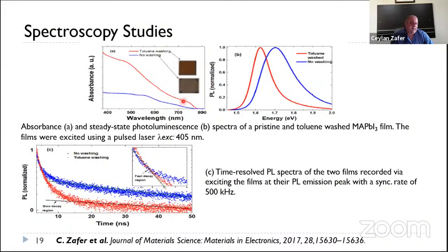This is also checked with the absorption and electronic spectra, and this makes a small difference in the optical properties of the perovskite. Here you see this enhances the molar absorption coefficient and also a small difference in the absorption edge of the material. And this can be easily seen in the photoluminescence spectra. There is a difference between the washed and non-washed materials.